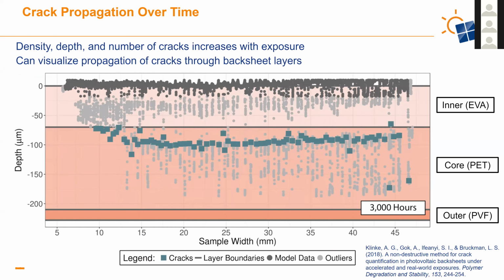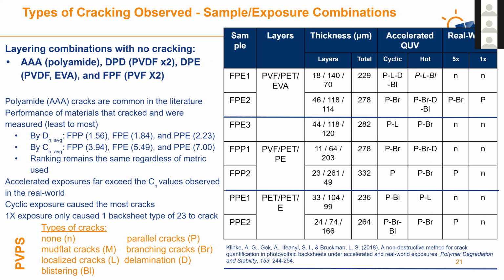And what we found is we didn't get polyamide cracks, just like a lot of the accelerated testing didn't see that polyamide cracked. And that's because we just had films and they didn't have that stress that they have inside laminated module where there's different stress conditions.